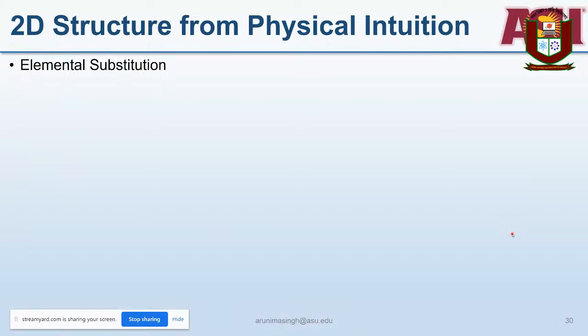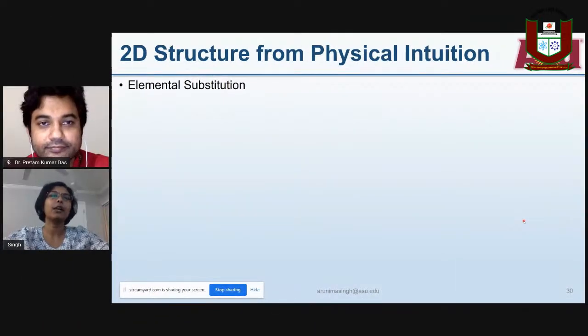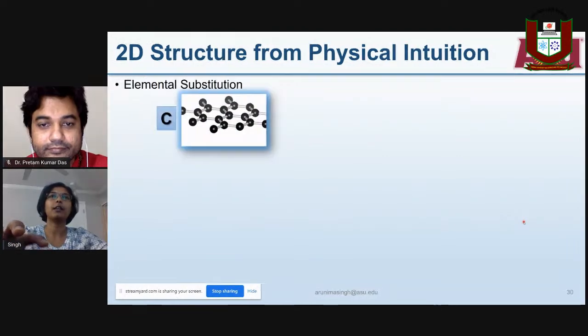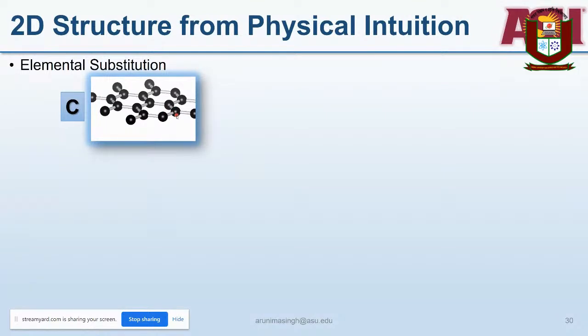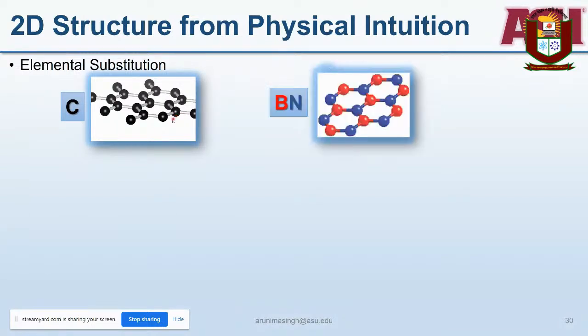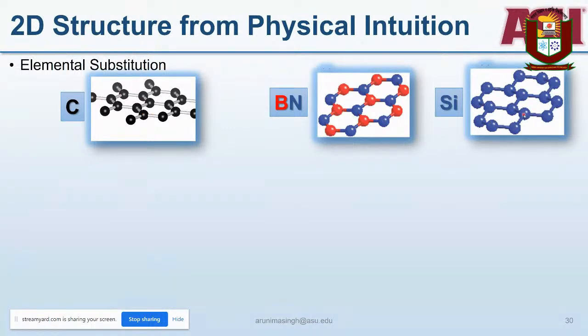So how were these two-dimensional materials actually discovered using computations? The first 2D material which was experimentally extracted was graphene. That was in 2005. And the structure of graphene is a honeycomb lattice with carbon atoms in it. What researchers realized is that perhaps we could substitute these carbon atoms with other elements and see if that would be stable. And that's how boron nitride was first studied, by doing elemental substitution in this structure. And silicene was the next one, and in silicene, the honeycomb lattice doesn't remain flat. The alternating silicon atoms are offset in the z direction. So one is at the top and one is at the bottom, and you have 2 sublayers.